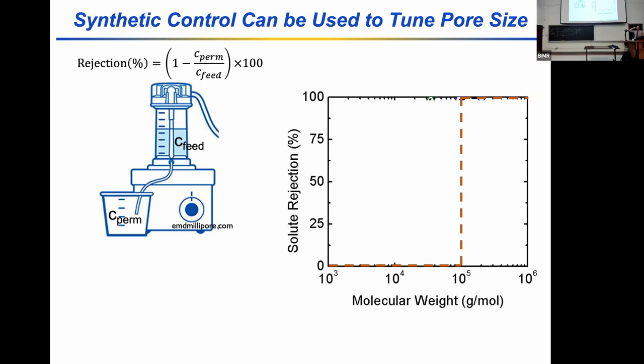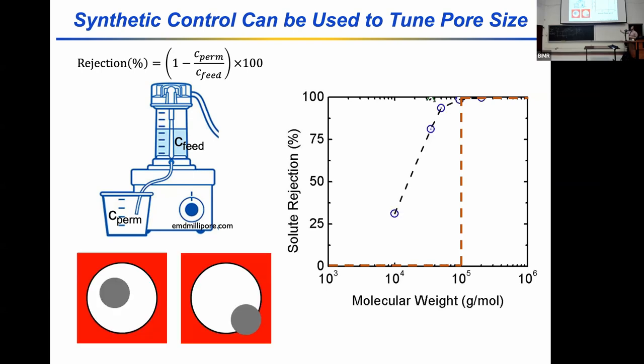A lot of people who make these from the material perspective really hope that we'd be able to get a step function molecular weight cutoff curve. And I'm here to tell you that's not the case, because once you have solute sizes that are comparable in size to your pore size, there's an entropic or steric hindrance that will prevent a portion of them from getting through, right? Our solute on the left, its projected area sits within the area of the pore, and so it would get through. Our solute on the right, its projected area sits outside the pore, and so it would get bounced off the pore wall and be rejected. That's why we end up with these slightly more dispersed rejection profiles, but they're pretty darn sharp when compared to hindered transport theories or theories developed for pores with a monodispersed size.